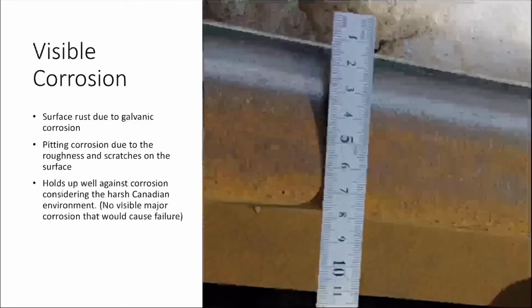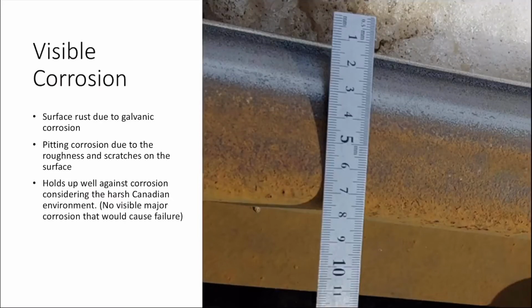Next, let's talk about the visible corrosion present. The section of the track that we observed appeared to have some surface rust. This can possibly be caused by galvanic corrosion from the exposure of salt, rain, etc. We also observed some pitting corrosion, which is due to surface scratches and the roughness of the track itself. Finally, in consideration, the railroad track holds up well against any major corrosion considering Canada's harsh environment and weather patterns.